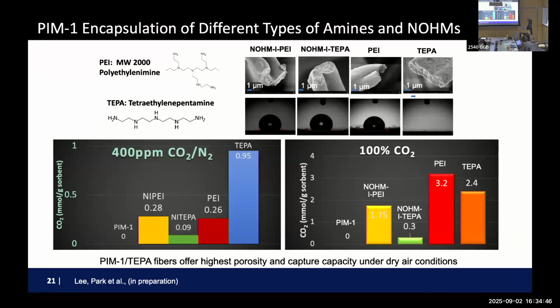Okay, CO2 capture in the direct air capture condition, which is exposed to the surface of the fiber, worked the best because there's no mass transfer limitation. Everything was on the surface. But all these materials are not so bad either. So we got really excited about CO2 capture using materials encapsulated in fibers.